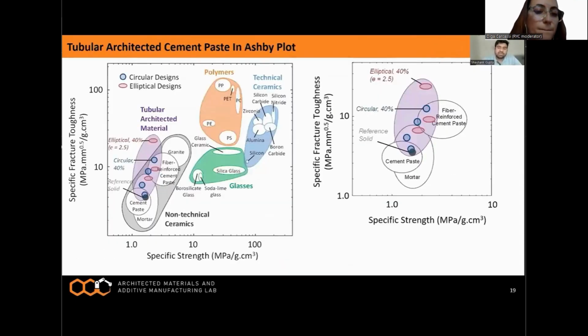To put it all together, let's see where all the samples lie on the Ashby plot. So all the tubular architected materials exhibited higher specific fracture toughness than the reference cement paste. Tubular architected material shows fracture toughness in the range of mortar to the upper boundary of the granite.